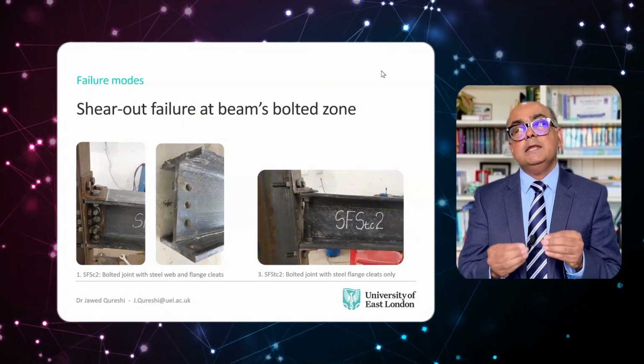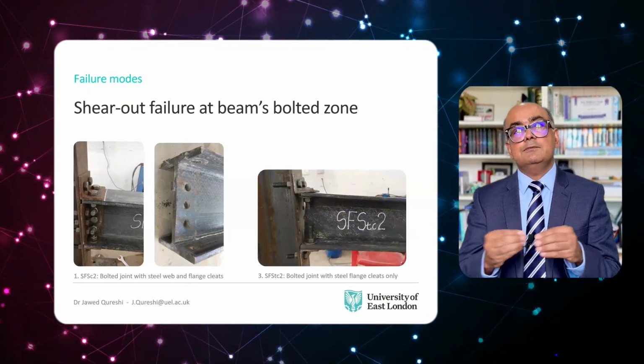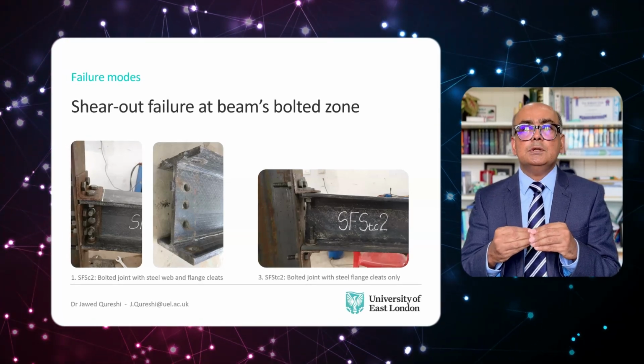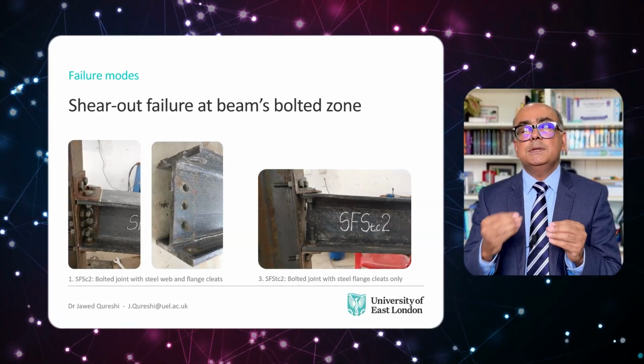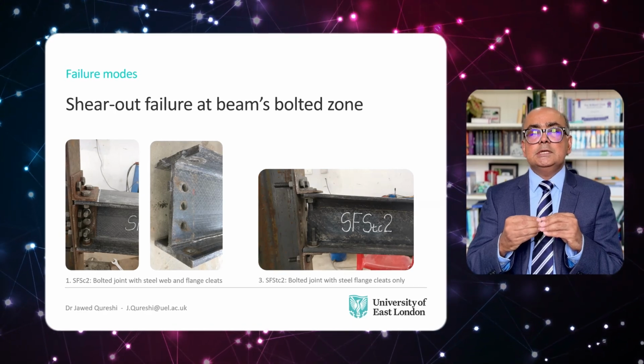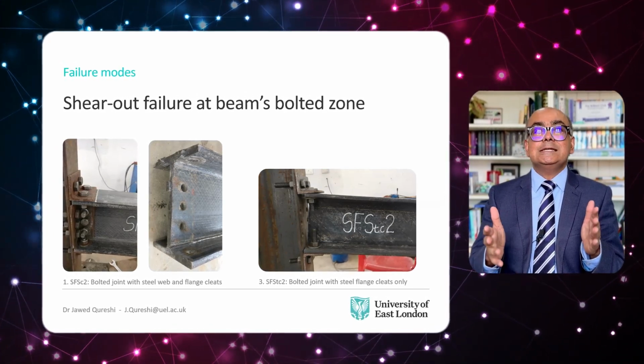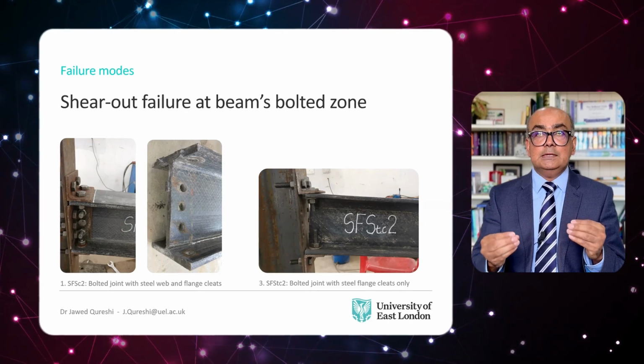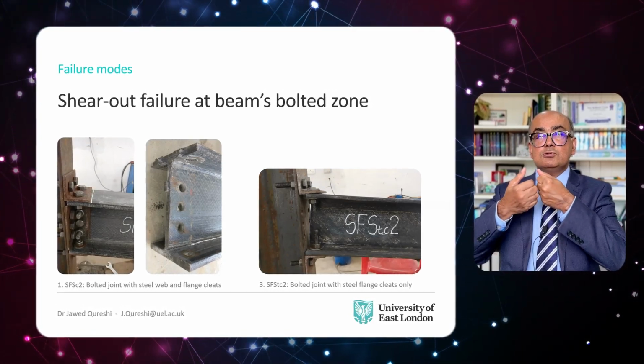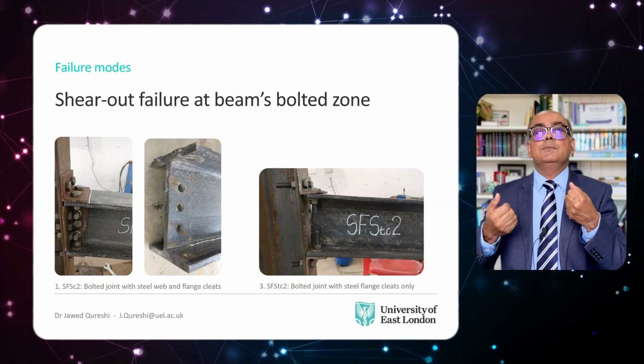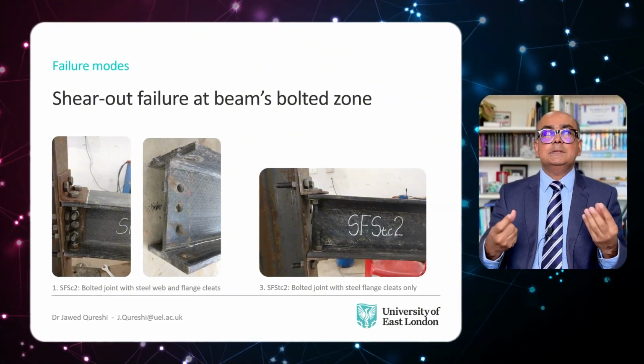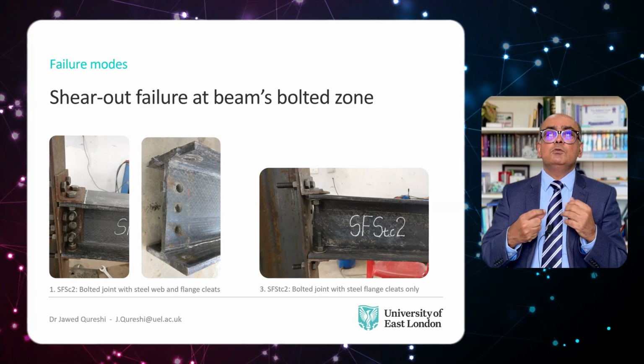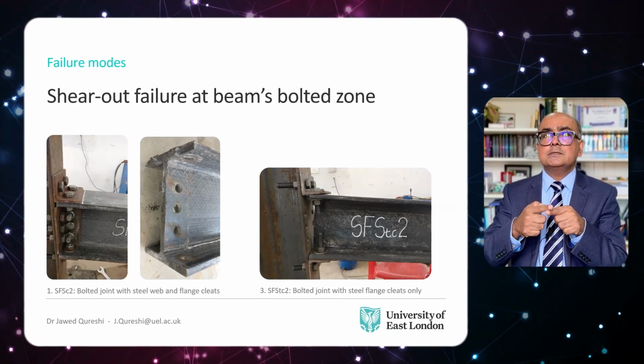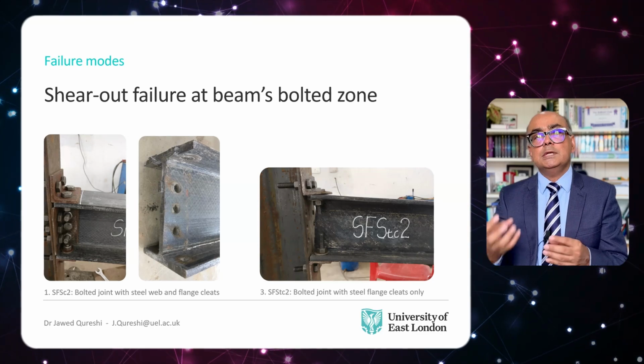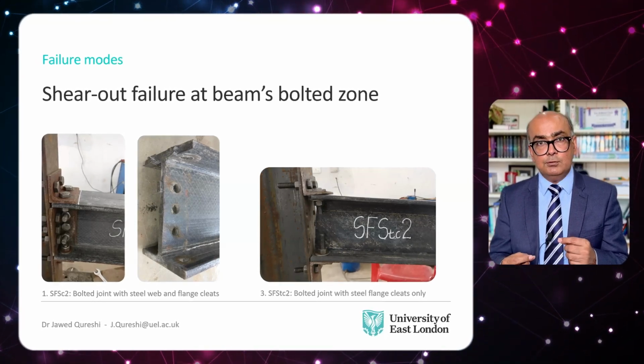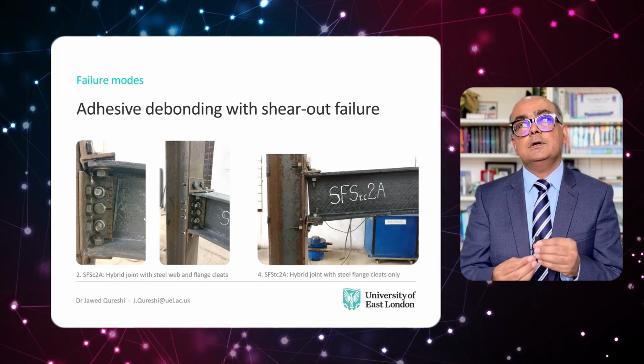There were 3 main failure modes that were observed in this research. First failure mode is shear-out failure of beam's bolted zone. The specimens with bolted steel cleats showed this failure where the bolts are trying to shear out of the beam. This type of failure happens in plate-to-plate connections with short end distances or when fibers are oriented in the tension direction of the force.